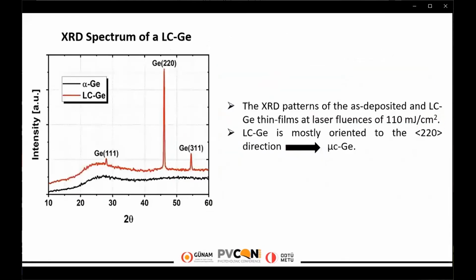And X-ray diffraction spectrum of sample irradiated with a laser fluence of 110 millijoule per centimeter square with 5 millimeter per second scan speed. The diffraction peak of the laser crystallization germanium is mostly oriented to the 220 peak direction, which indicates microcrystal germanium domains. The film is preferentially oriented to the 220 direction.